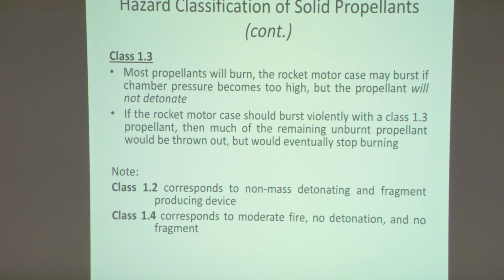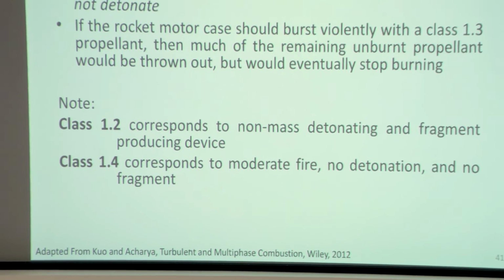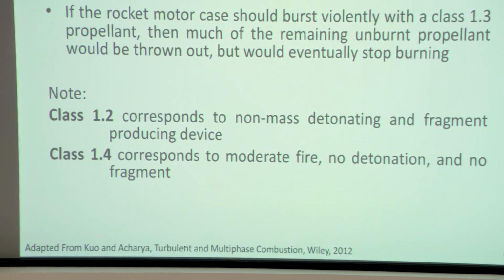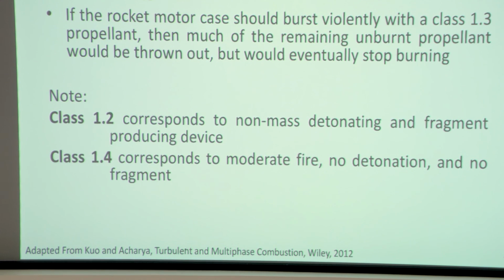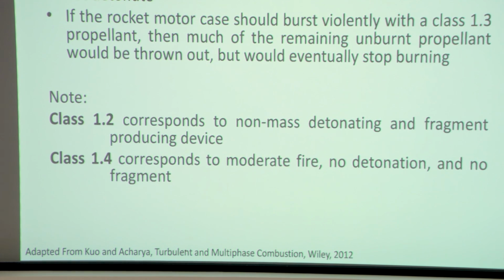If the rocket motor case should burst violently, say with a class 1.3 propellant, then much of the remaining unburnt propellant would be thrown out, and then eventually it would stop burning because there's a lower pressure deflagration limit typically for many propellants, where if I'm at atmospheric pressure, they just won't burn. And then I also note there's 1.2 and 1.4. The 1.4 pertains to fire characteristics, no detonation, and the 1.2 corresponds to non-mass detonating and a fragment producing device.